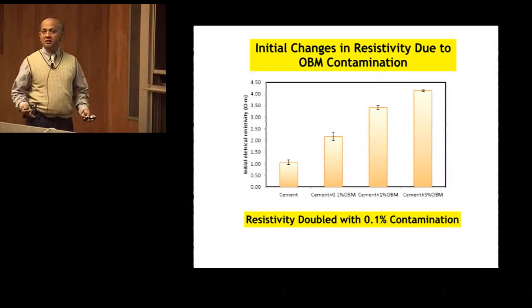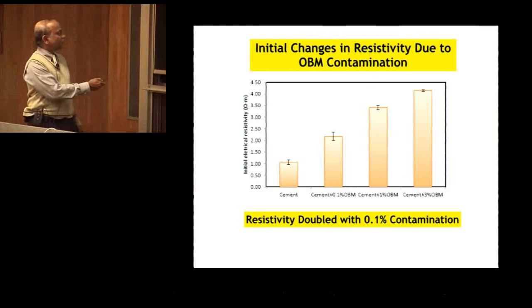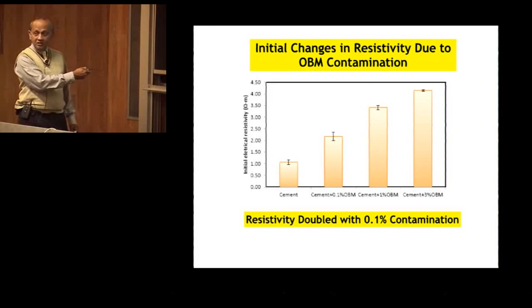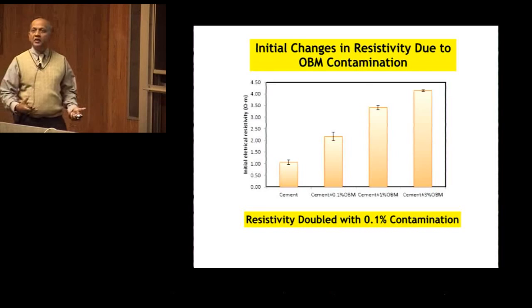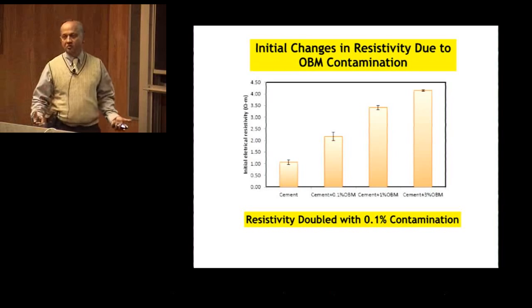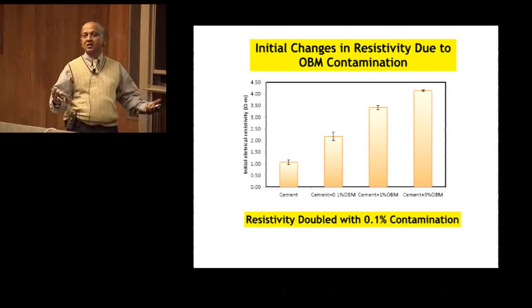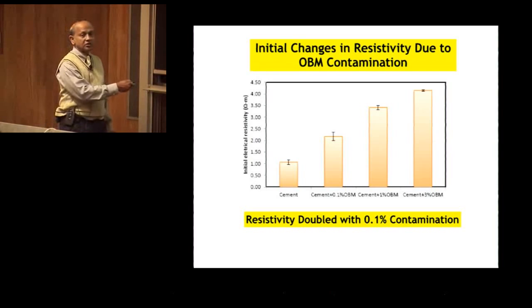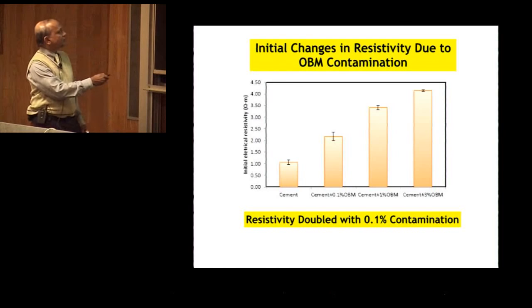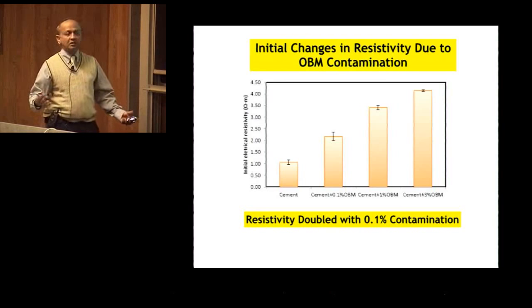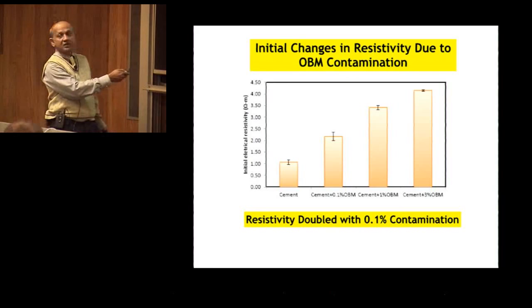Then if your cement is getting contaminated with a drilling mud, the same cement, as I told you, has a resistivity of around 1. If it is getting contaminated with about 0.1% oil-based mud, this is another popular drilling mud they use, because they don't use any particles here, and this is popular with some of the formations. So with 0.1% contamination of the cement, this goes from 1 to over 2, doubling the resistivity, and you can see how it's increasing rapidly.